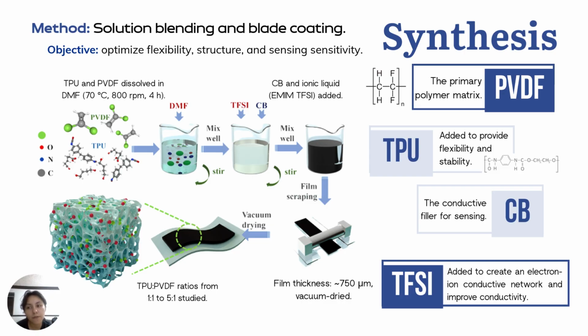The TPU PVDF TFSI CB membrane was prepared using a simple solution blending method. TPU and PVDF were dissolved in DMF, then carbon black and the ionic liquid TFSI were added to form a uniform composite solution. This mixture was coated onto glass to create a 750 micrometer film, dried in a vacuum oven and trimmed for uniform thickness. Finally, silver adhesive electrodes were attached on both sides of the membrane, completing the fabrication of the temperature sensor.